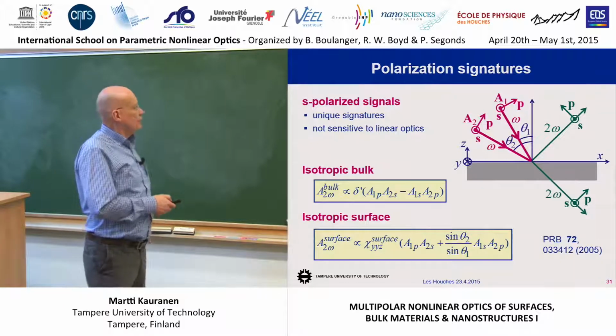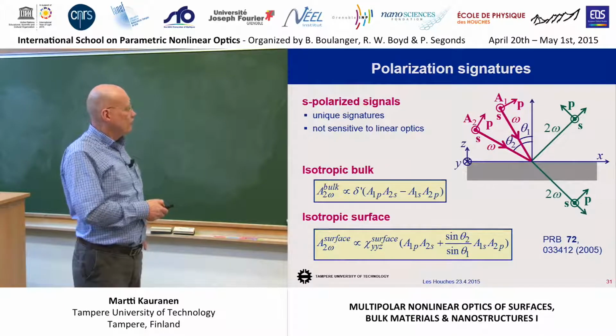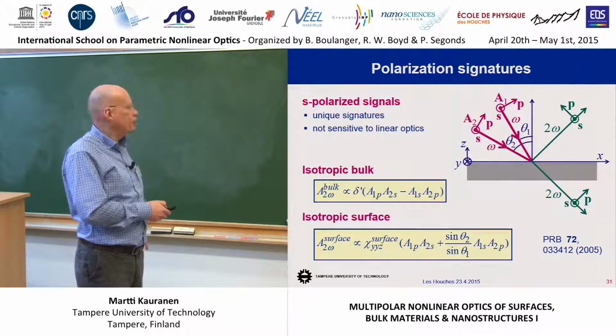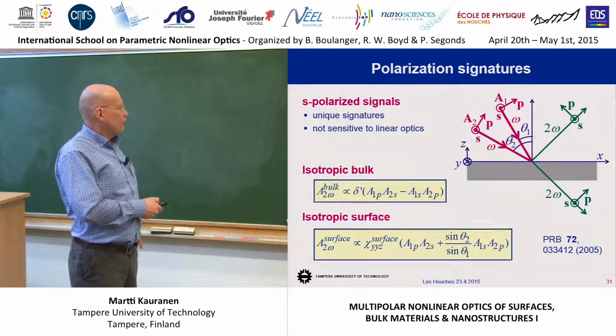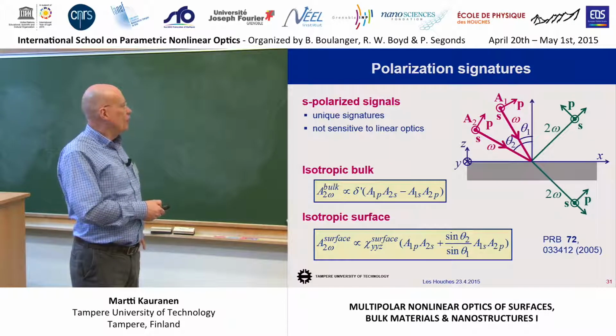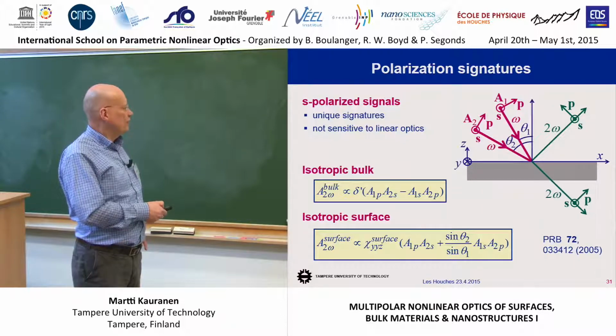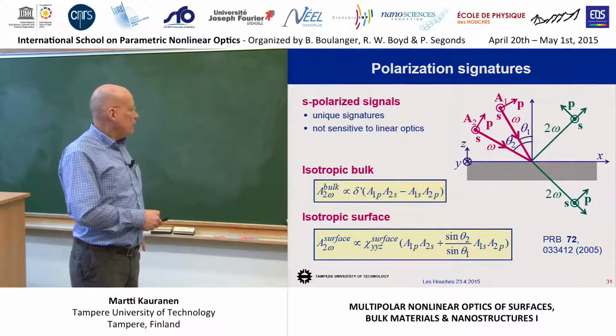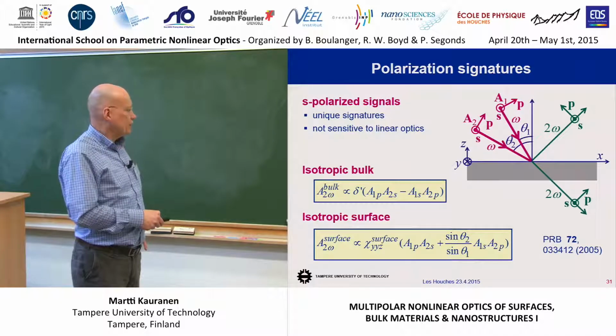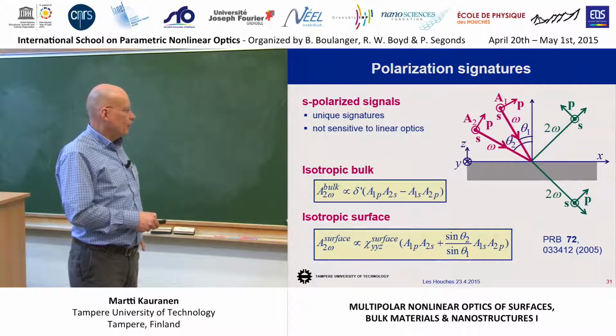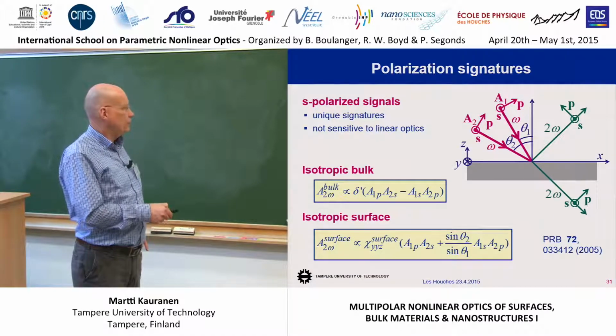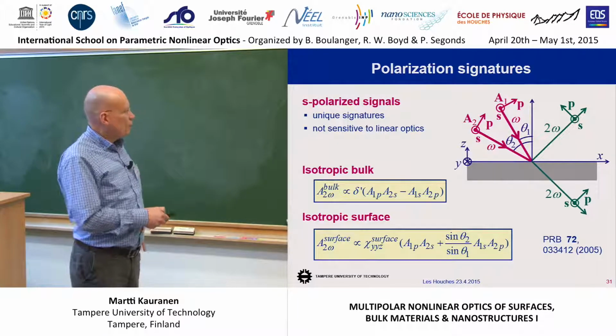And the key here is that if you look at the theoretical expressions we have, and again work a few pages of algebra, the bulk contribution that depends on the delta prime parameter goes as the P component of beam 1 times the S component of beam 2 minus 1S 2P, okay? And you're detecting now the S polarized signal. Then the surface response depends on just one tensor component, YYZ, and it goes as 1P times 2S, 1S times 2P. The same combination as here, but here we have a minus sign.